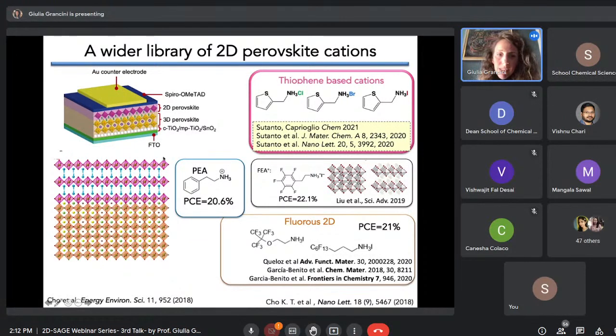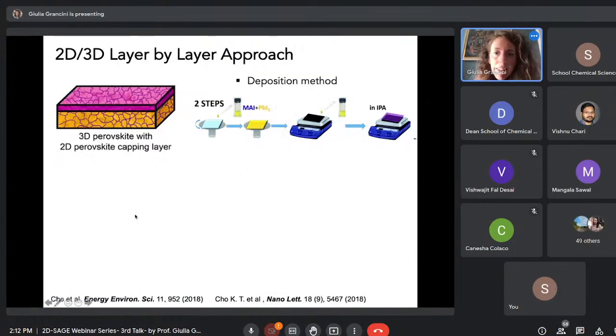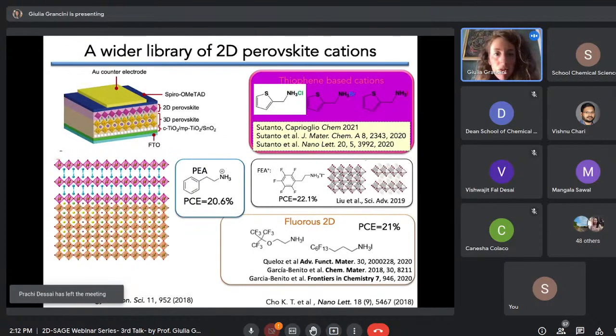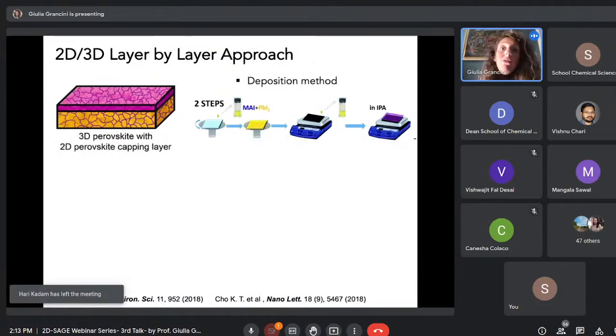To form the 2D perovskites, you can choose the organic cations that can be phenylethylammonium, can be thiophene-based cations, fluorinated derivatives, fluorinated 2D. So you can see that there is a very large library of 2D cations that can be used to form the 2D perovskites. With this layer-by-layer structure, the most interesting thing is how do you deposit the 2D on top without dissolving the 3D underneath? So first of all, the process. Well, the process is very simple.